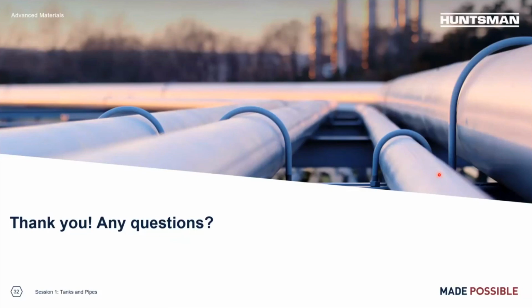Awesome. So I think I have this last question. Do you have any toughener that can be used on the hardener side? Yes. During the slides, I did mention we have amine terminated tougheners, HYPRO ATBN and 1300X45 ATBN. This is amine terminated, so you want to use this on your amine side to bring up the system's overall toughness. We also saw some applications where people are using tougheners on both sides. Sometimes they add epoxy-based toughener into the epoxy resin side, and they also add some amine terminated toughener into the curing agent side, and sometimes they got pretty good results using the combination. So yes, we do have these kinds of options.